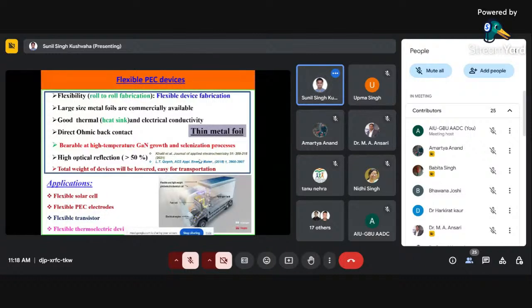Another thing is, when we have a high temperature growth process, for example, sometimes we have gallium nitride or some other materials, like MoS2, this requires 600, 700 degrees Celsius. So for that process, a polymer based substrate, a PET substrate, can't be used for this kind of application. So that is one approach.